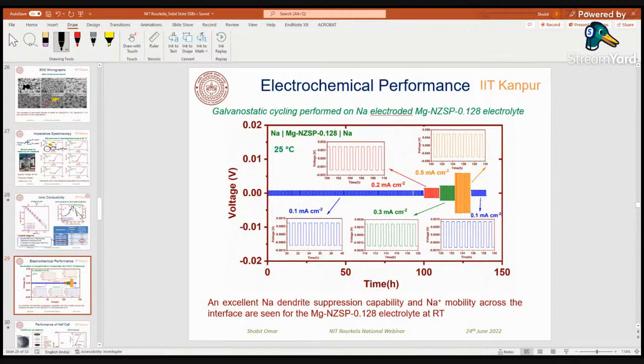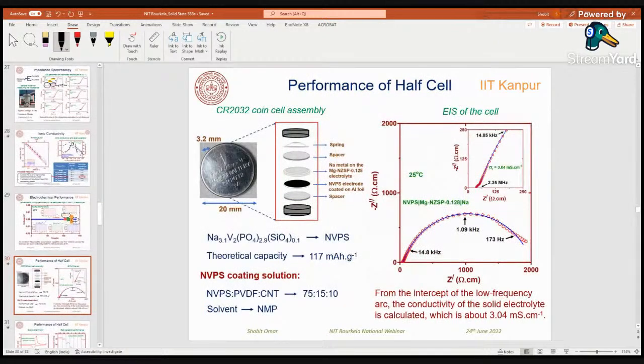We did the galvanostatic cycling performance testing at different current rates, and we got a stable cycling performance. You can see that this is at 125 cycles, which we did at 0.5 milliampere per centimeter square, and then we went back to 0.1 milliampere per centimeter square. We got a stable performance, which shows that there is an excellent sodium dendrite suppression capability of this electrolyte material. Then we fabricated the solid state cell.